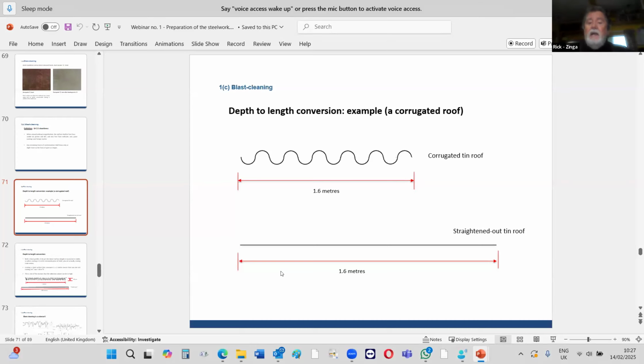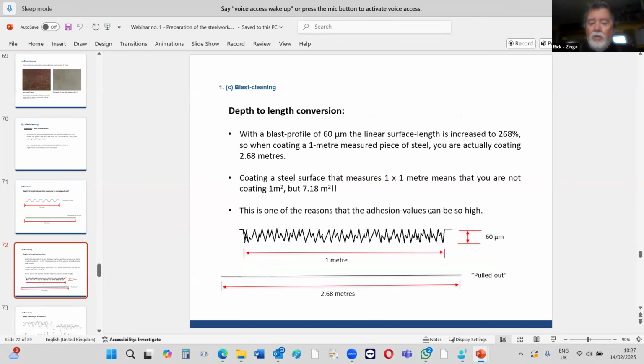So if you take a sheet of corrugated iron and it measures, sorry, that's actually the wrong thing there. That's actually 1 meter. I beg your pardon. I don't know why it's got 1.6. When you get a 1 meter wide sheet of corrugated iron, if you pull it straight out, it becomes 1.6 meters in width. When you take a blast profile, again, 1 meter long, and you blast clean with slag to 60 microns, if you could pull that straight, it actually comes out to 2.68 metres.